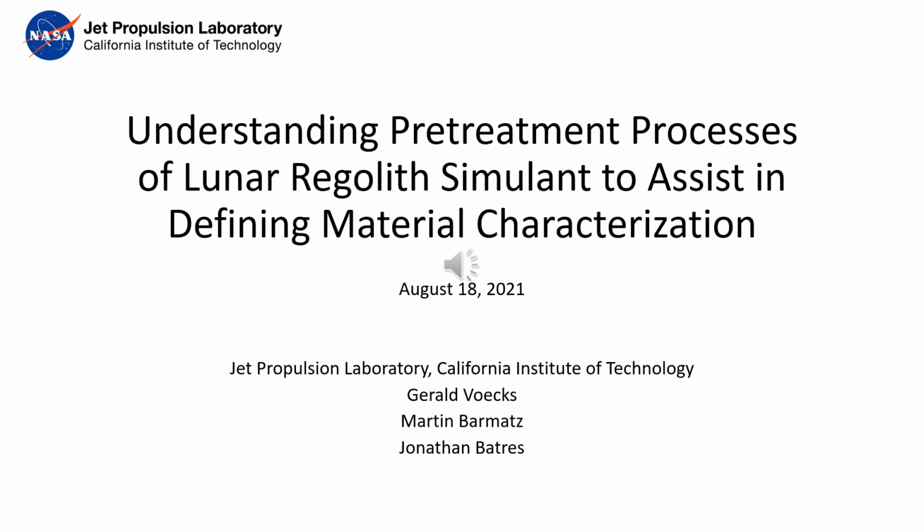degrees. In summary, heating terrestrial lunar regolith simulants under vacuum will drive off volatile species not associated with lunar material and is a means of removing them. Although this approach suggests removal of water and carbon dioxide volatiles is relatively successful at temperatures below 800 to 900 degrees centigrade, sulfur dioxide removal from material that's contained in the simulant appears to require temperatures that are much higher.